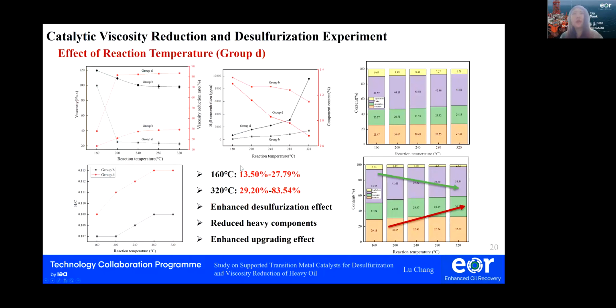The previous results show that groups D and E have the best performance. Considering the economic issue, group D was selected to study the effect of reaction temperature, and group B was conducted as the reference experiment. The first figure shows the viscosity reduction rate of the oil samples of group B and group D. After the reaction at different temperatures, the viscosity reduction rate increases from about 10% to nearly 30% at 160 degrees, and reaches more than 80% at 320 degrees.